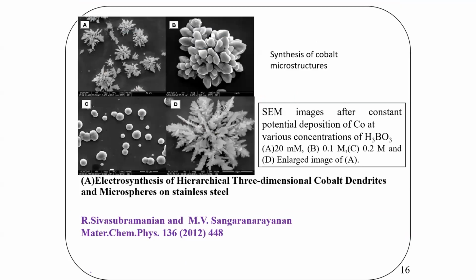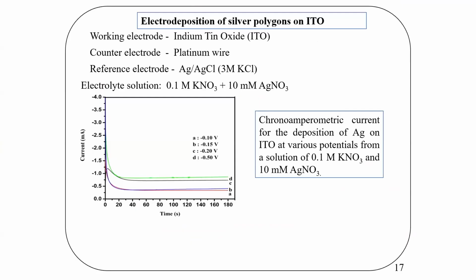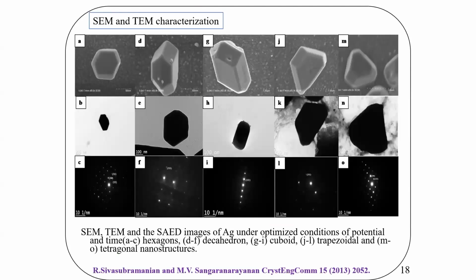Then here you can see we have prepared cobalt microstructures using constant potential deposition at various concentrations of boric acid. It acts as a structure directing agent, 20 millimolar, 0.1 molar, all these various geometries are coming for cobalt. Then we have many other things. Silver polygons. This also we prepared on indium tin oxide. Using chronoamperometry, you can see working electrode, counter, reference electrode, and so on. And then you'll see very good geometry. You see here, various geometries are coming for silver polygons.